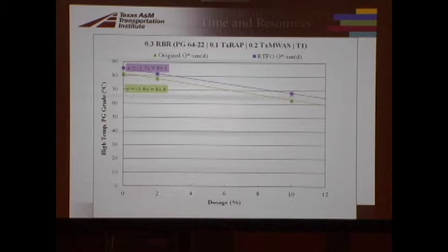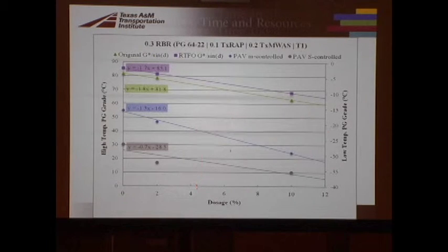The green line is the original G-star over sine delta. What was its PG high temperature grade at the threshold? And then the purple is the rolling thin film, because you gotta figure out what both of those are and what's the limiting one. And then on the right side, we're gonna graph 2 more lines, and we're gonna put the low temperature grade. And here we have the M controlled in blue and the S controlled in gray. And what you see here is the distance between these 2 lines is actually the delta TC value. And as we keep adding recycling agent, the distance between those 2 lines is getting closer together, which is good.